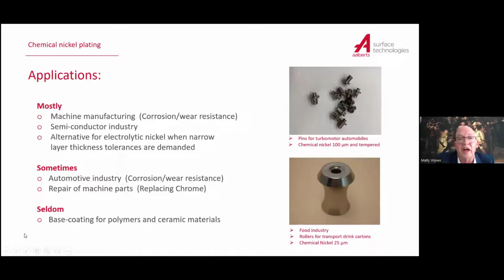What is it used for? Machine manufacturing. That's one of the biggest parts where it's used, especially for corrosion and wear resistance. And of course, you can work with very tight dimensions. That means with the electrolytic processes, you always have your dog bone effect. You don't have that with chemical processes. That means, working in these days where we think about layers and dimensions in microns instead of millimeters, it's good to have such a layer which can exactly take over the dimensions.